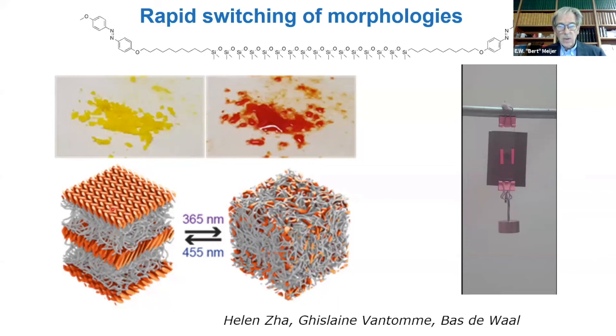So as a result, we have a material which is a paste. If you irradiate with 365, it becomes azobenzenes inside of siloxane, so it becomes a lubricant. If you now shine light on it of 455, it goes back to a paste. And I hope that I can show you in here. You see two glass plates and some weight connected to it. And we have glued them together with this paste.